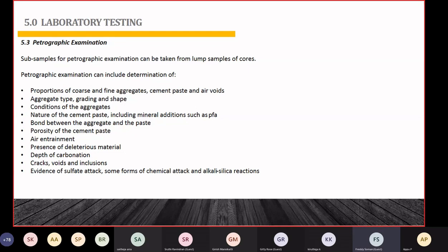The condition of the aggregates, nature of the cement paste, including mineral additions such as PFA, slag, bond between aggregates and the paste, porosity of the cement paste, air entrainment. Yes, air content we can find out from the petrographic examination, as well as deleterious materials in the concrete. Depth of carbonation we can find out in petrographic analysis as well. Cracks, voids, and inclusions, evidence of sulfate attack, some forms of chemical attack, and alkali silica reactions. Particularly, you might have heard about ettringite. Sometimes delayed ettringite can cause damage.